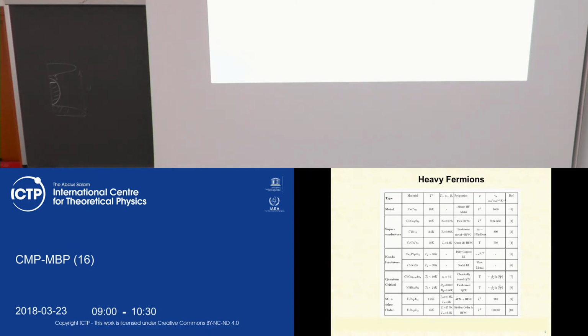So some of them are superconductors. And you see that the temperature of superconductivity is of course incredibly low, on the order of a few Kelvin or even less than a Kelvin. However, as I said, the effective mass of quasi-particles, measured through specific heat measurement, is very high, of the order of 1,000.